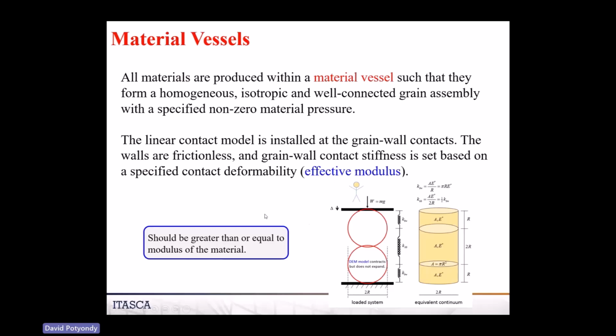And the value we use for that should be approximately equal to the final modulus of the material. Because what those walls are really doing is just applying forces to the system, and we want the overlaps between the walls and the balls to be relatively small. We would get that if we set the wall modulus about equal to the material modulus. If the wall modulus is really low compared to the material modulus, then you're going to get these giant overlaps between the walls and the balls, and we don't want that.